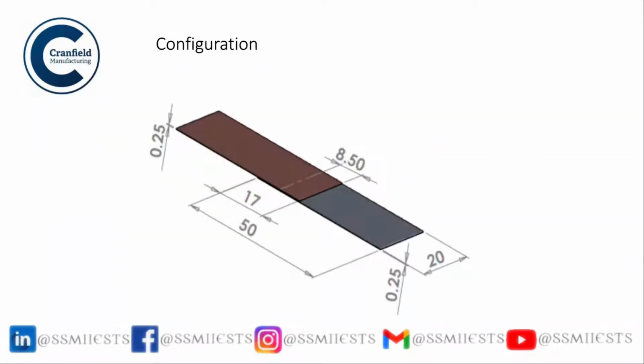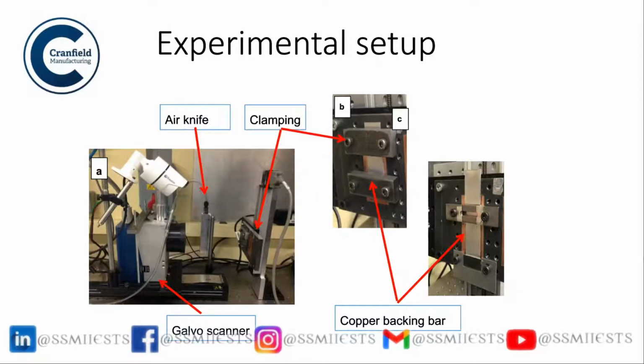So this is work which was done for joining of copper to steel, stainless steel. And you see this is the overlap. Sorry, this is not stainless steel, it's copper to aluminium. And you can see here the experimental setup which was used in the lab, and we used a galvo scanner because the laser needs to be moved very, very fast. And there's the copper backing bar that we have used in this particular application.